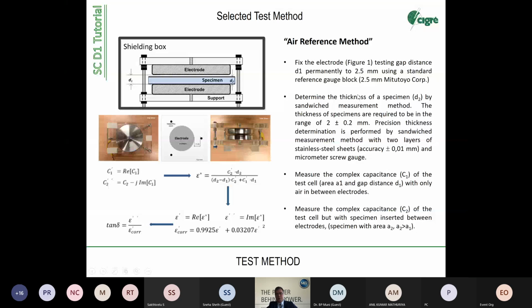And so here is one challenge, of course, the adjustment of the distance. We did this by precise distance measurements or length measurements. You have to determine the thickness of a specimen. Normally, when you get material samples out of a laboratory, the quality is not better than 2 plus minus 0.2 millimeter. So you have a certain kind of scatter because of the production and the method of how you produce the samples.